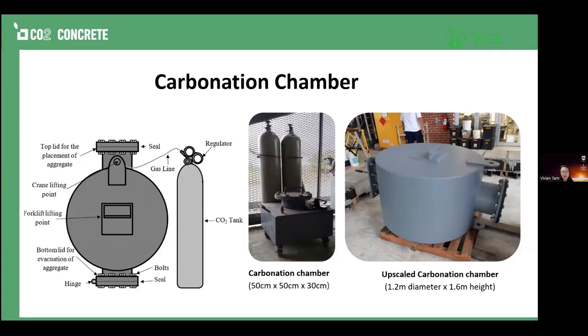How we arrange it is the aggregate is put on top. Normally we use a bulk bag because we can put 1 ton of material in. We put in the bulk bag and then they will do the magic in terms of the carbonation inside. Once the carbonation process is done, the aggregate will come out at the bottom. Then we lift the whole chamber up using the heavy lifter in the laboratory, and then the materials can go out. And this is how we carbonate the materials. I cannot tell you exactly the process of how we're doing it because it is under a confidential agreement.